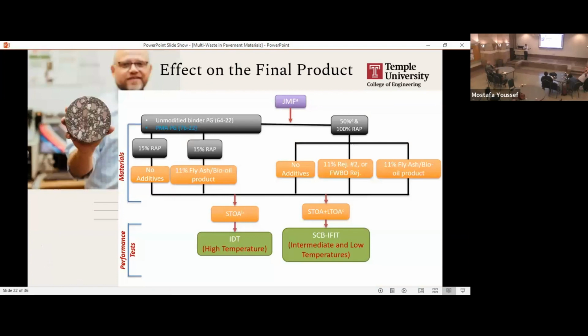So again, like we did before, let's look at the final product and see what the mixture will do with these kinds of materials. In this case, for example, the control will be 15% RAP. So there's 15% of the mix already waste material, combined with another 11% from the fly ash and the oil. So we're trying to maximize the amount. After that, we also tried 50% and 100% RAP. 100% RAP means the entire mix is fully waste material.